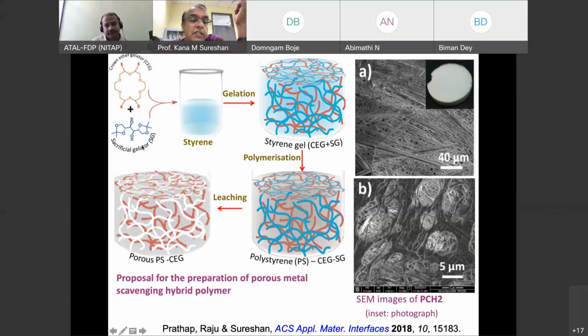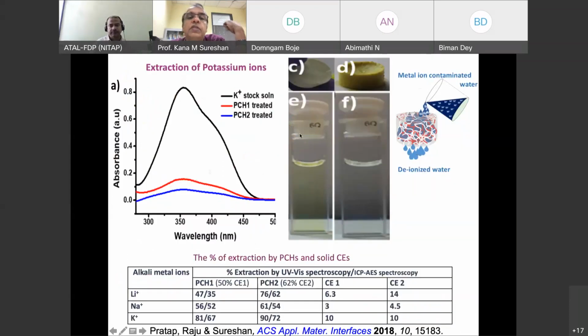How do we make channels? Just wash it away. Just take the solid cube and wash it with methanol or even water. This gelator is water soluble, so it will go, and in the places where this gelator was, it will make channels. Now what you have is a porous polystyrene matrix in which you have crown ethers inside. This is an SEM picture of that. And we have used this material, this tablet actually, made out of that porous material.